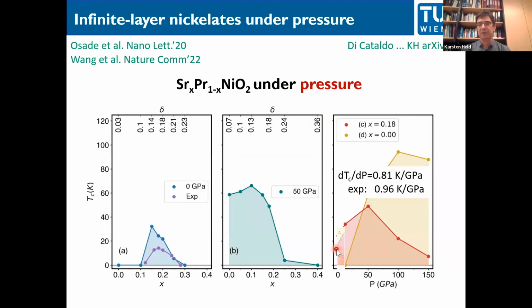And if you see that here, it has a very similar slope. So about 1 Kelvin per gigapascal increase in TC. And that very much agrees with the existing experiment. It's not a prediction, but a confirmation. And we see here that TC will further increase before it dramatically decreases. So let's look at this 50 gigapascal, where we have the maximal TC. And that is the second phase diagram as a function of strontium doping.